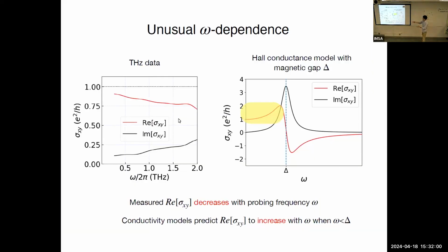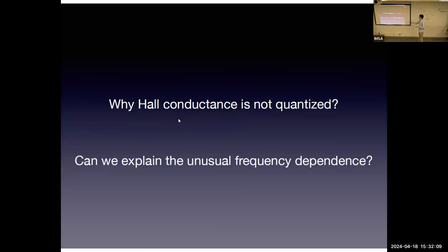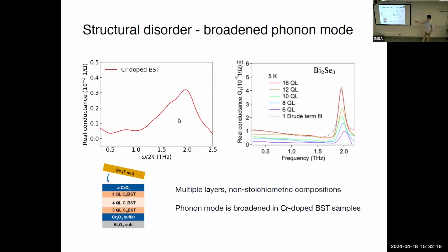So we saw this dependence, which is in contradiction with most of the theories, and we started puzzling why that is. There are two questions: why it's not quantized, and also why the frequency dependence is quite the opposite. The very first thing we saw was the longitudinal conductance as a function of frequency, and as you can see, there's a very wide mode at higher frequencies. If you compare bismuth selenide, which showed the quantized effect, which is a 3D TI showing quantum Hall effect, this feature is very narrow. What this broadening tells spectroscopists is that there's huge structural disorder in the system, and it's not surprising because we have so many layers of different dopings and different stoichiometric compositions. It's apparent, but it shouldn't really affect the Hall measurement because this is a longitudinal effect.